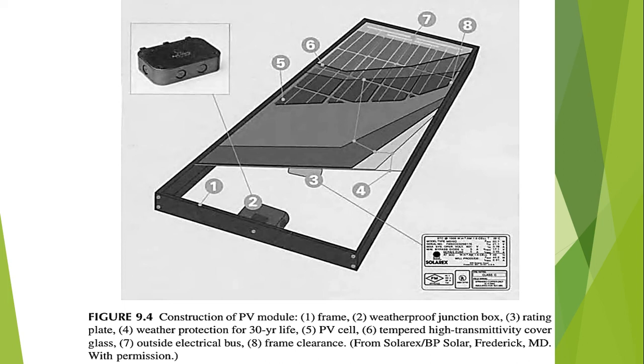The lamination on either side of the photovoltaic cell provides shock absorption and helps protect the cells and interconnecting wires from vibrations and sudden impacts such as hailstorms. A high-quality EVA film with a high degree of cross-linking can be the difference between a long panel life and failure due to water ingress. During manufacturing, the cells are first encapsulated with EVA film before being assembled within the glass and backsheet.